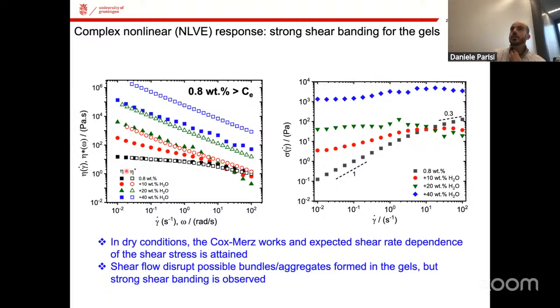You see that when there is no water, so dry conditions, the two viscosities are basically the same. But as soon as you form the gel, the steady shear viscosity is always smaller than the complex viscosity, or the viscosity measured in the linear viscoelastic regime, meaning that the strong shear flow is basically destroying all these sort of bundles or clusters that form during the gelation process. And it seems that the more water you add into the system, the larger the difference becomes between complex viscosity and steady shear viscosity.